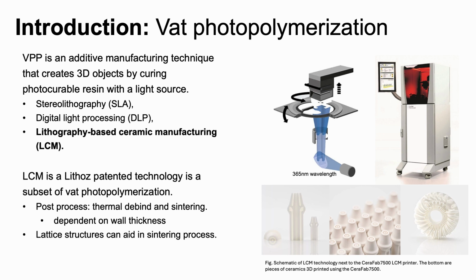It's a method that uses a ceramic slurry that is dispensed to a transparent vat. Then the movable build platform is dipped into the slurry before being exposed to a visible blue light. Each layered image is projected onto the slurry, and it's produced by a digital micromirror device in combination with a projector. This process repeats until the 3D printed part is completely built.